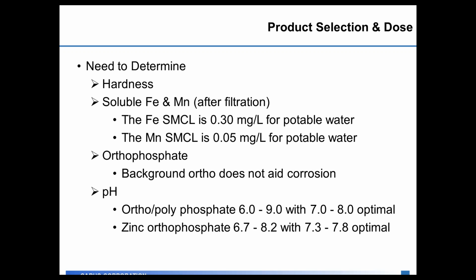And then finally, what's the pH of your water out there in the distribution system? With a blended phosphate, you can be between pH 6 and 9. Ideally, we'd like you to be between 7 and 8 to be optimal. And specifically, if you use a zinc orthophosphate, you really want to be between pH 7.3 and 7.8 to make that the optimal process, or on the far side, 6.7 and 8.2 with those products. Typically, we'll look at the water quality at the plant and then out in the distribution system when we make a product selection and a dose.